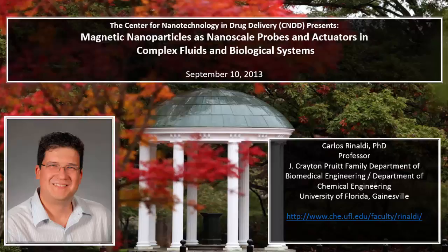So we think this indicates that what's going on is that if you have particles that are not targeted, or cells that do not overexpress a receptor, you get some particles attached to membranes, some particles internalized into lysosomes, some energy being delivered locally. That can lead to some disruption of lysosomes, but not enough to really damage the cell. But if you have targeting and you have overexpression of the receptor, and that leads to receptor-mediated endocytosis and accumulation in lysosomes, when you apply the magnetic field, you disrupt a large number of lysosomes.